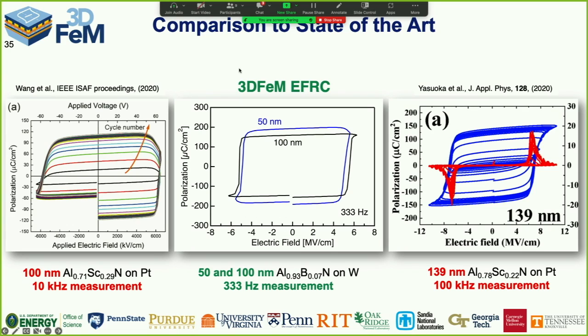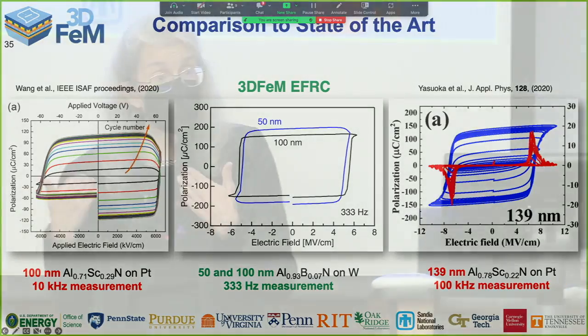Here is the aluminum boron nitride analog. You can see at 50 and 100 nanometers thickness, so comparable to these, much nicer shaped hysteresis loops, and we were able to measure it at much, much lower frequencies. We're hiding less. So this material, the band gap doesn't drop as fast, so it looks pretty appealing for this application. And so let's build it into a ferroelectric field effect transistor.